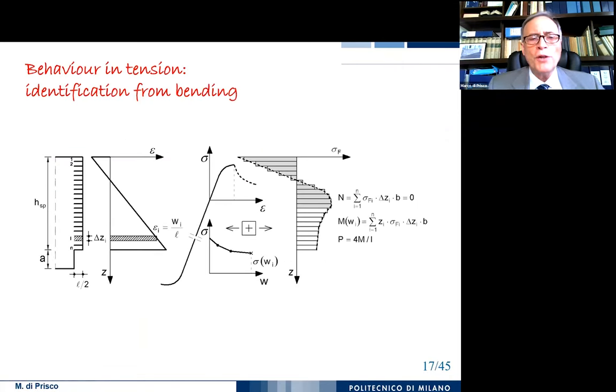Of course, if we want to define the constitutive law in uniaxial tension starting from bending, we could use, for the identification, the classical equilibrium relationship, imagining that the strain, obtained as a ratio between the crack opening and the characteristic structural length, remains plane. This is the same concept adopted for reinforced concrete structures.